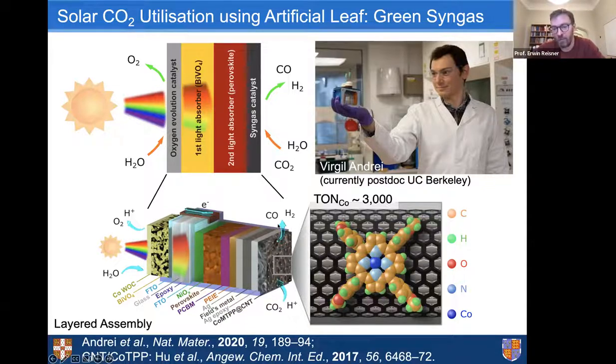And in this case, what we have used is a nanotube, actually a nanotube forest, so a high surface area material that's conducting. And then we pi-pi stack and integrate this cobalt porphyrin catalyst that has been known to reduce CO2 to CO. And in our case, it works with a turnover number of about 3,000. It's a fairly good system in terms of the catalyst.